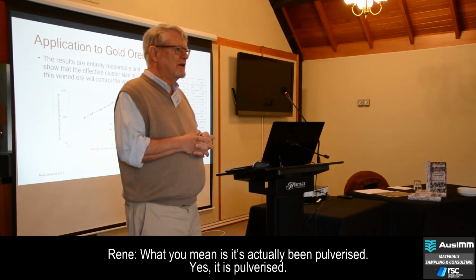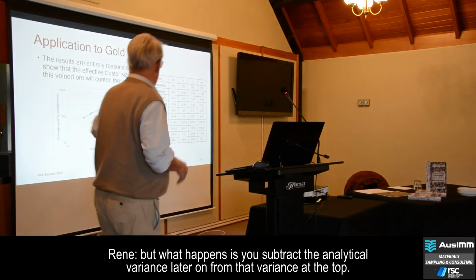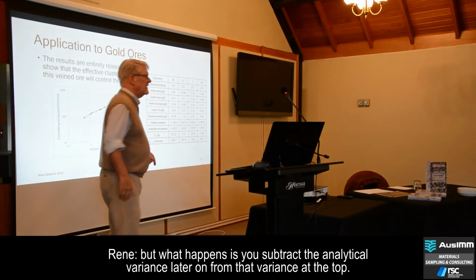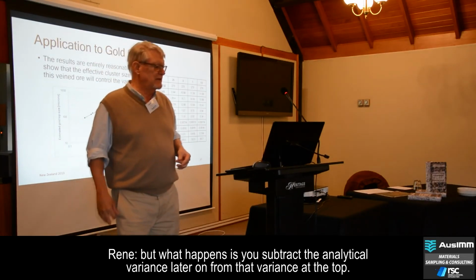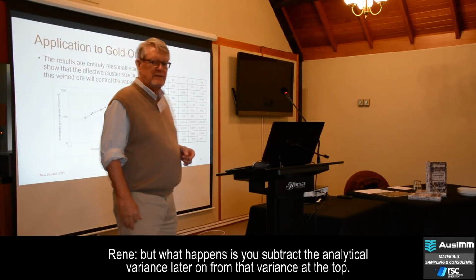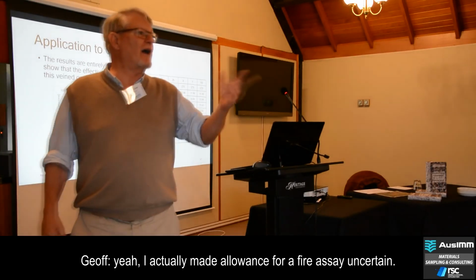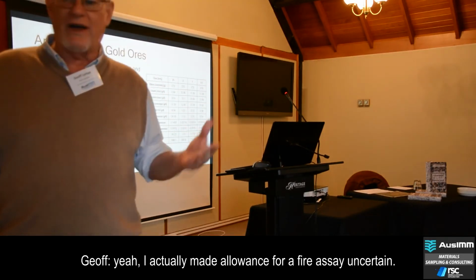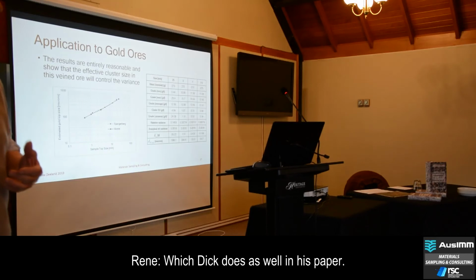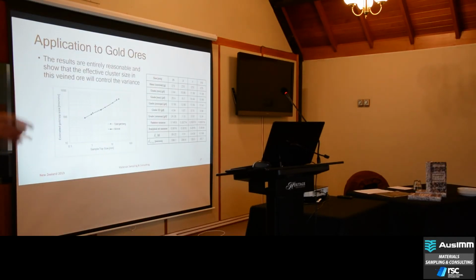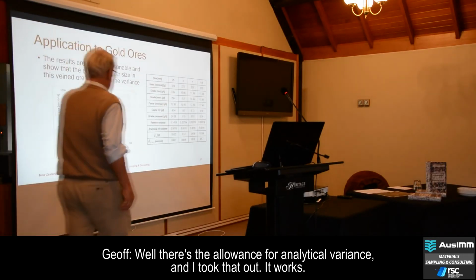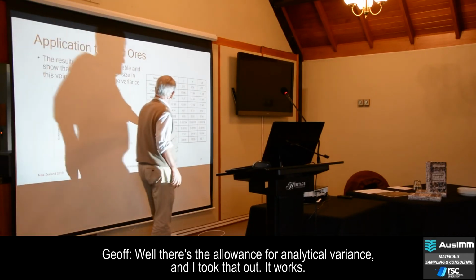Yeah, it is pulverized. What happens is you subtract an analytical variance later on from the variance at the top. So I actually made allowance for a fire assay uncertainty, which Dick does as well in his paper. There's the allowance for analytical variance, that's 4%, and I took that out.